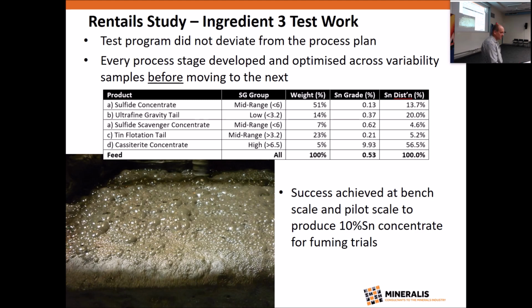It took about 3 to 6 months, I can't remember exactly, and there was a particular focus on the sulfide flotation because that gets rid of most of the mass, and also the ultrafine gravity because it was a fairly novel thing at the time, and we weren't too sure about scale-up. But after our efforts, we eventually cracked over 55% tin recovery into a nearly 10% tin concentrate. And all our further efforts after that just improved the results before we conducted a full and extremely painful pilot plant to make enough concentrate for ultimately successful fuming trials.